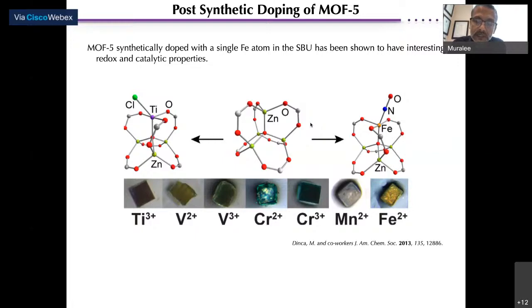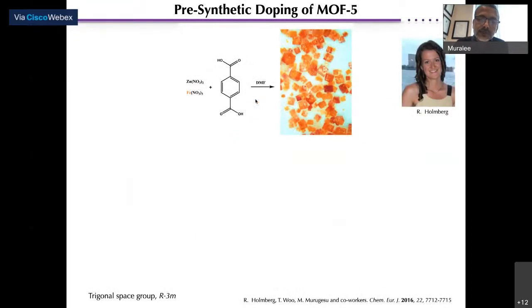So we thought, what would be nice. By the way, these structures have been resolved by powder XRD and computational methodology. There was no single crystal report at that time. So we were wondering, is it really possible to see what happens to the zinc site when different atoms come nearby? Does it stay stable, as MOF5 is often claimed to be? We weren't so sure of this feature. So what my student Rebecca Holmberg did is basically react MOF5 with a small percentage of iron nitrate in this reaction.